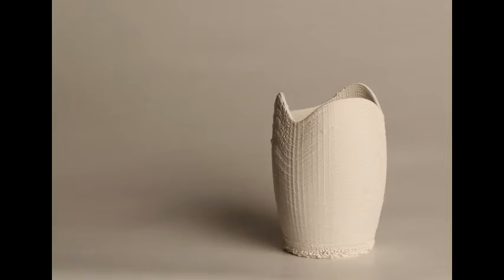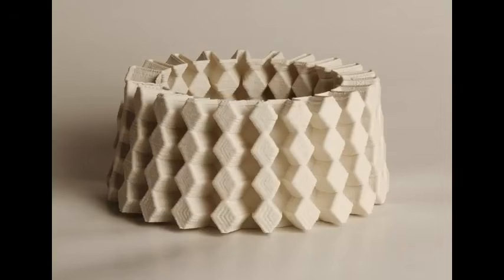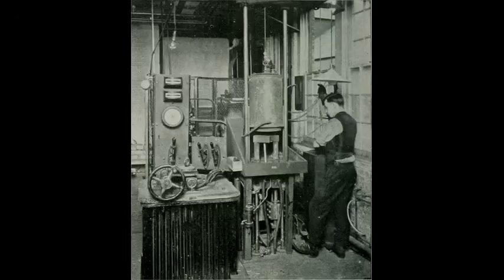Its mechanical behavior came from hardness and compressive strength, but also from the elimination of defects. A perfectly bonded crystal lattice is extraordinarily strong. Real ceramics fail at pores, inclusions, oversized grains, machining scratches, or surface cracks. Advanced ceramic manufacturing is therefore largely the science of controlling imperfections. Powder purity, particle size, pressing uniformity, firing atmosphere, peak temperature, grain growth, surface finish, and inspection all influence whether the final part survives. That same logic explains why alumina spread after the war.